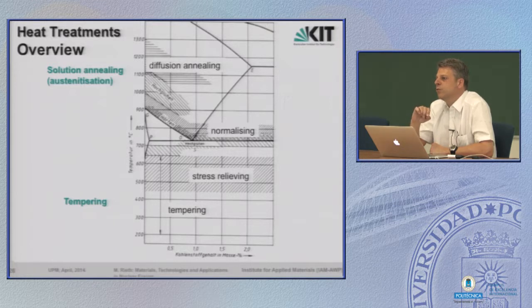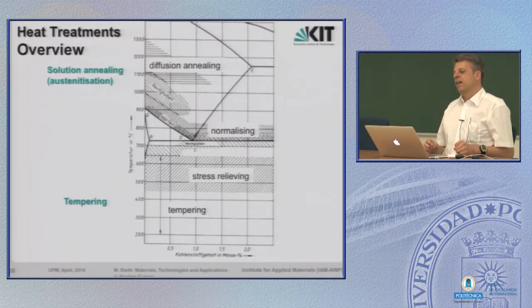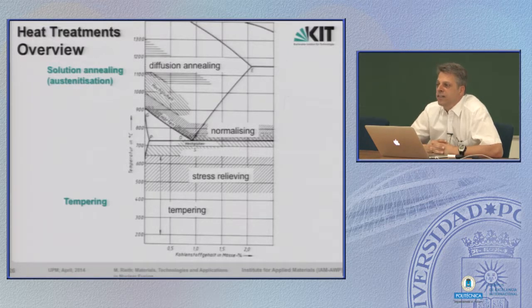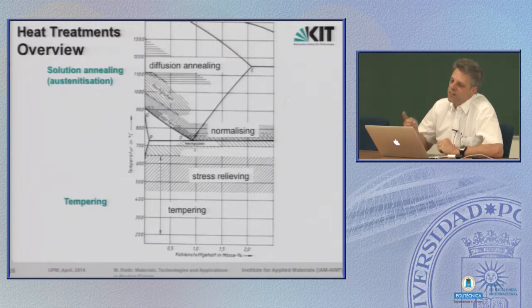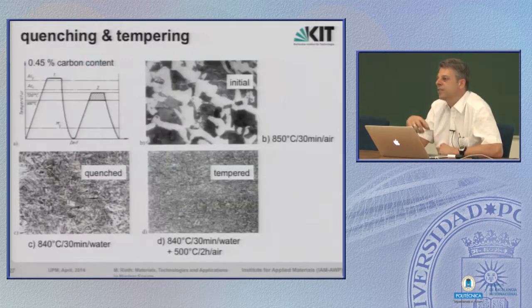And then this is a real good material, because in principle you have done nothing else than produce one of our basic hardening methods, namely produced a very fine structured material. And this is the primary use of martensitic steel for structural application. You produce them, you temper them, then they are not so brittle anymore, but they are still strengthened, which means they have an enormous yield strength, tensile strength whatsoever, but they are also ductile. They can be bent, formed, whatever. They don't break as easily. Of course, in this form, they are not so useful for knives at the edges, but they are useful for pipes and other structural application.